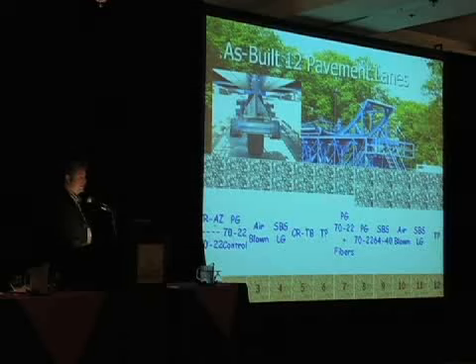4 inches of the control, an air-blown binder, the other modified binders, the crumb rubber terminal blend. We have our fiber binders. Then we switch into a 6-inch layer, where instead of 4 inches of asphalt, now we have 6 inches of asphalt. And we have, not the same, but a few of the core binders we're looking at there. What we are using to load these pavements is a 425 super single, and that's also a product of some research done at Turner-Fairbank.